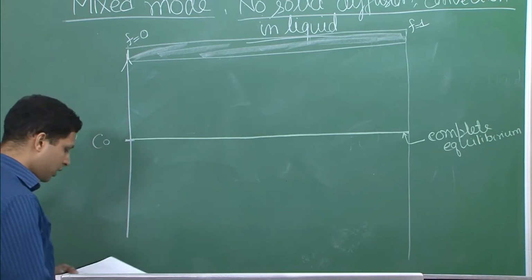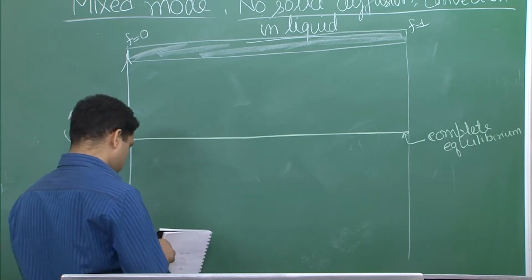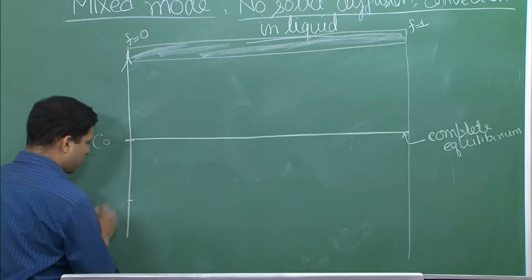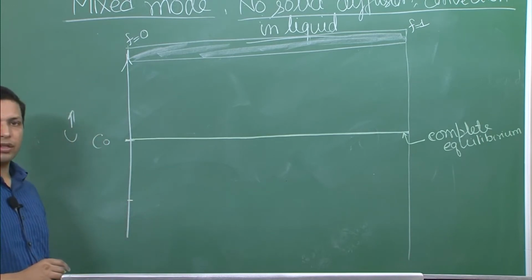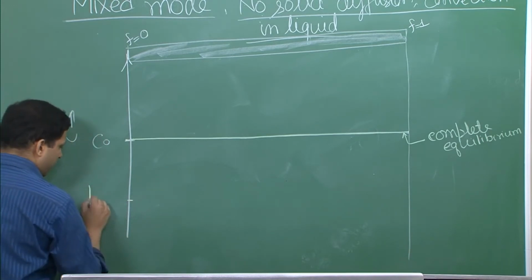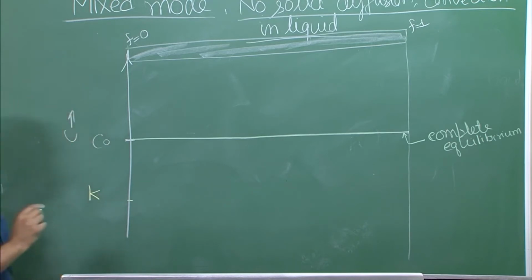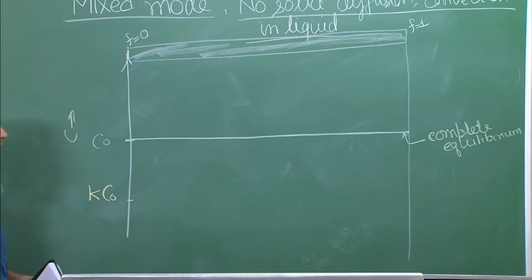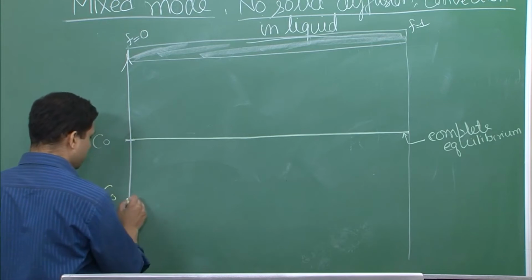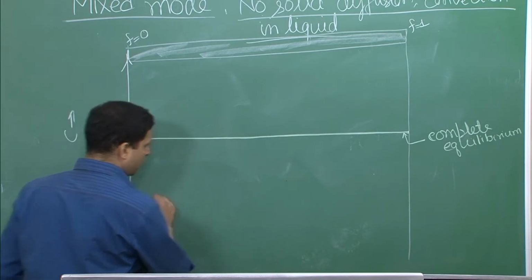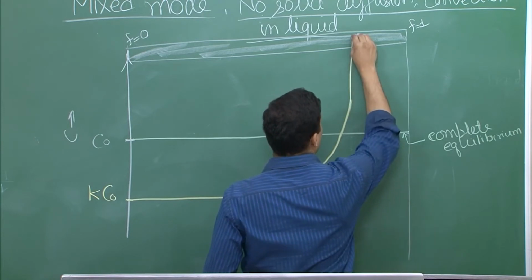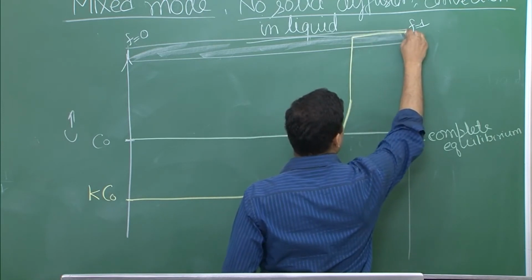Next was the case when we discussed the Scheil equation, that is when there is no diffusion in solid, but complete mixing in the liquid. So, let me draw it, and in this respect there will be a concentration which will become very important. Whenever there is no diffusion in solid, the first solid that forms will have the concentration K naught C naught, and therefore, let me put it very distinctly over here, and so this will have a concentration profile like this.